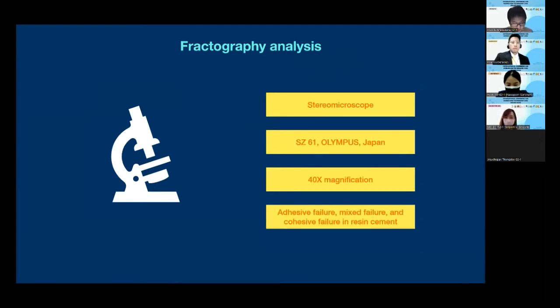For the mode of failure, it was inspected under the stereo microscope at 40x magnification. 3 failure modes were seen in this study, including adhesive failure, mixed failure, and cohesive failure. But cohesive failure in this study was found only in the resin cement layer, not in the dentin structure.